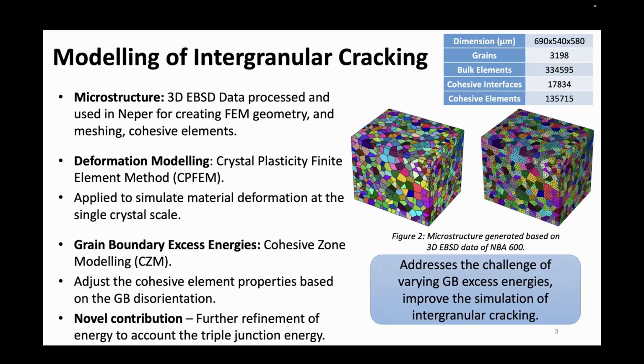With the realistic model, we then proceed to the simulation part, where we want to model the deformation. By doing that, we're using the crystal plasticity finite element method to simulate the material deformation at a single crystal level. And then we expand this to the grain boundary excess energy, which is very important in the simulation of intergranular cracking. For this, we use the cohesive modeling method. We first study based on the surface energy of nickel alloys. Then we adjust the cohesive property, basically the grain boundary energy, based on the grain boundary disorientation.